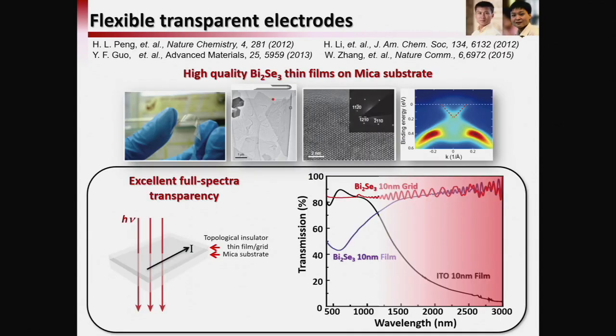Then we talked to Yi Cui and Hailin Peng. Now he's at Peking University. He was the postdoc of Yi Cui back then. So Yi Cui was capable of making everything at the nanoscale. So they were able to grow the topological insulator, in this case bismuth selenide, as a nano thick film, about 10 nanometers on a transparent substrate. And we measured the transparency, and it turns out it's pretty good for the film.